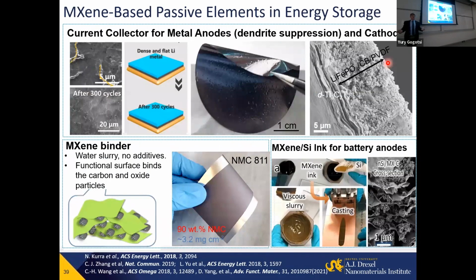Also, what is important, I stressed it several times, you can make thinner films compared to metals. You can use it as a current collector, but much thinner and much lighter compared to metal. Moreover, MXenes, for example, are stable in halogen-containing environments. So you can use, for example, chloride electrolytes that cannot be used with metals. It's a major pain for these applications, or for electrochemical water desalination. And they also suppress dendrite growth.